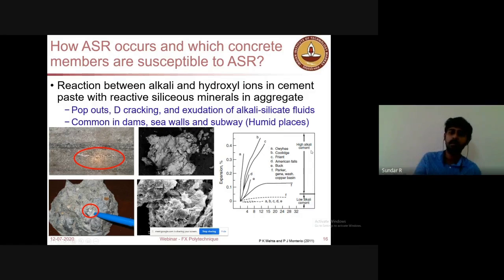alkalis. For the silicate from the aggregates to react with alkali in the cement, there must be an abundant supply. When we have a low alkali cement and reactive aggregates, you will observe much lesser expansion. But when you have a high alkali cement and a reactive aggregate, the situation will become dangerous. So when you work in a certain area, if you came to know that you are using a high alkali cement based on the material assessment, as well as when you suspect the aggregates will be reactive, you should be careful about this ASR.